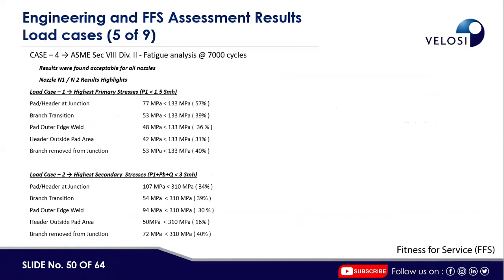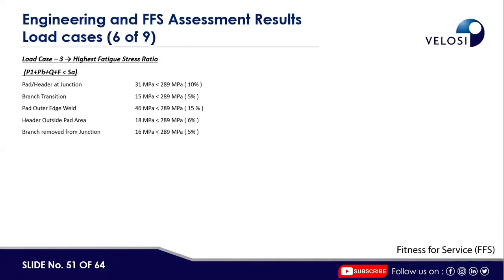Now the results of Case 4. You can see that under load case 1, the highest primary stress ratio should be less than 1.5 Smh. So here the maximum load ratio is 57% in Case 1. Case 2, this is the ratio of the various loads. And Case 3, the highest fatigue stress ratio, which is shown for the various components, right?